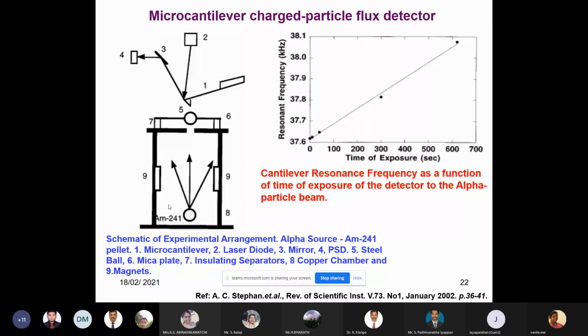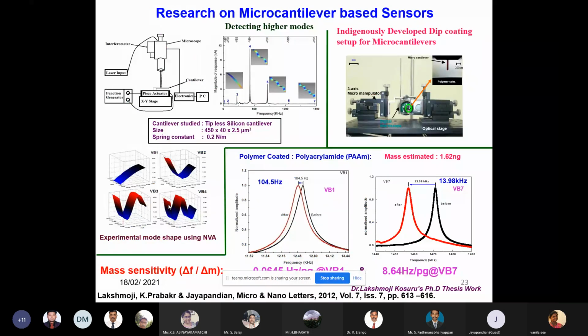They plotted the graph for time of exposure with respect to resonance frequency change. The cantilever was vibrated with the piezo material, a piezo exciter. By vibrating it, because of the alpha particle radiation, the cantilever deflects. Likewise, they are getting a very linear measurement with different timing exposure. This confirms that the cantilever can be used as an alpha particle flux measurement very easily. Then this is research in our laboratory.